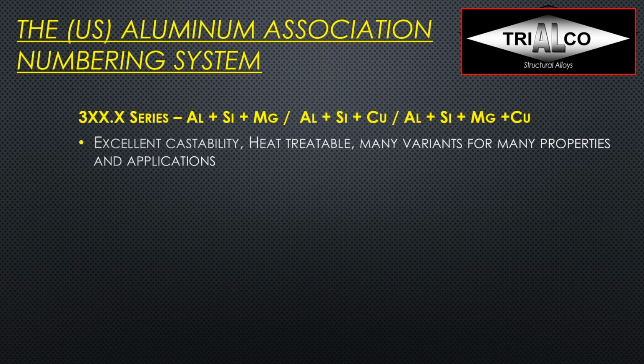They all have in common excellent castability. They're all heat treatable. As soon as you have strengthening element magnesium in there, you will get the mag silicide hardening, or with copper, we have also seen very heat treatable. You get very interesting property packages, and you can vary it depending on aging, for example, things like that. So you can really tune the alloy extremely well just with the chemistry and then the combination with heat treatment.